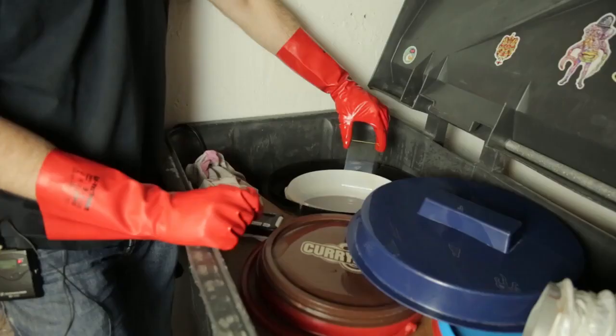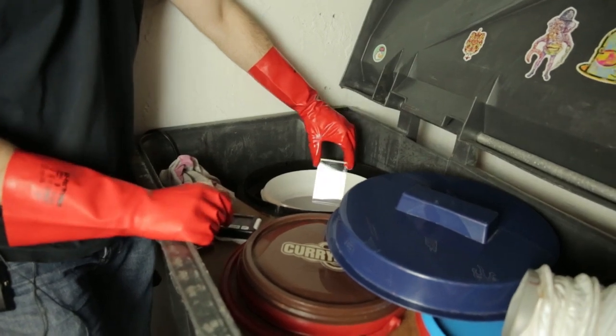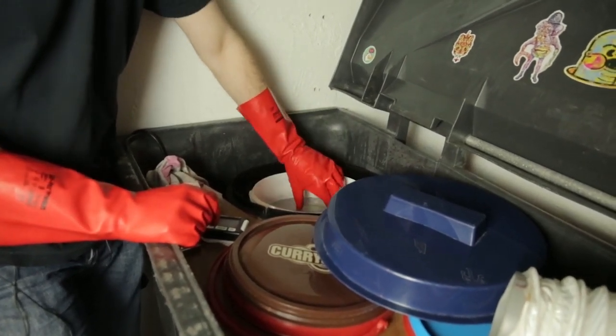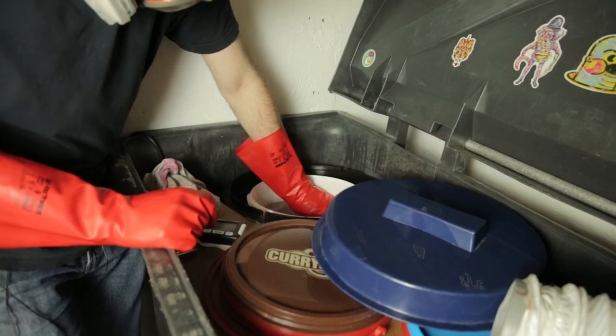After I've taken the plate out of the 84% bath and wait a while, I will start to see a hologram reflection at the top of the plate. Once I see that slight reflection, the plate is ready for the final bath. The 100% alcohol bath can be heated up to 40 degrees, but today it's unheated and at room temperature. I put the plate smoothly into the 100% and it will stay in there for 3 minutes.